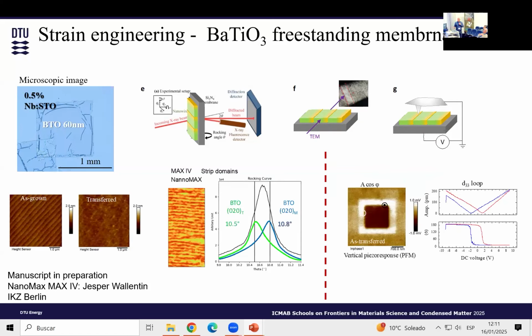Our findings are the following. So this is the as-grown, this is the transfer, so we can still see the terraces after the transfer. I guess you can see it here. And the interesting thing that we observe from the X-ray is that we can see modulation in the X-ray. So these are scattering signals from the X-ray. So these lines represent a scattering signal from the 0 2 0 BTO.